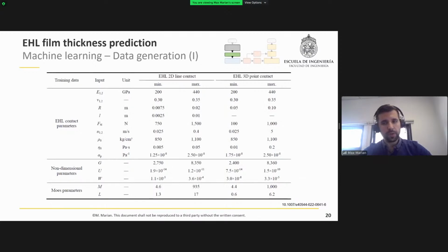This slide shows the parameters that we vary within the given boundary conditions for the 2D line contact and the 3D point contact. They were sampled using Latin hypercube sampling with 1,500 and 1,000 datasets respectively. Moreover, for the 2D case, we investigated to what extent a reduced database with only 600, 300, and finally only 100 data points affects the prediction quality.